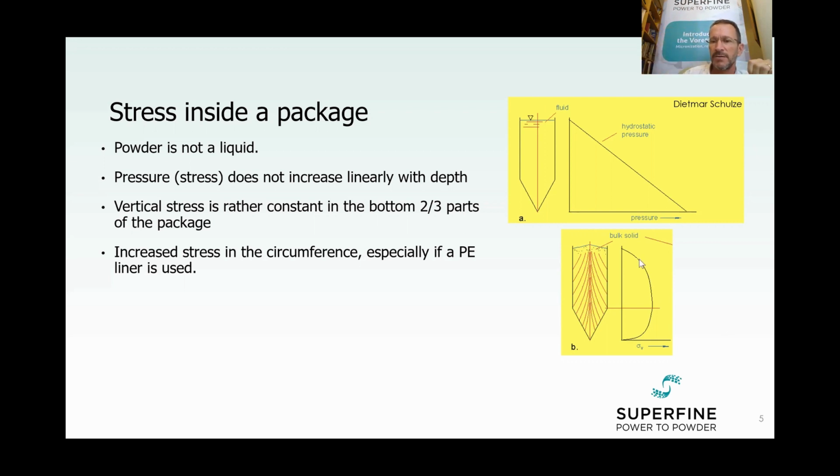And this is why, because the pressure is already the same. If this pressure is enough to create compaction forces and solidification, then keeping the package only this high will not make a difference. So the rule of thumb is that after 1/3 of the height, it's already the same.